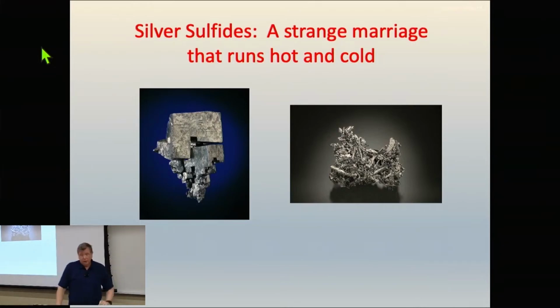So the classic way to look at that is acanthite. When we go buy an acanthite and we find a nice one, that's a Guanajuato piece there on the left-hand side, it looks cubic. In fact, that is the high temperature form of silver sulfide. But as we lowered the temperature, it froze in that structure from the visual perspective, but internally it has a monoclinic structure. All those sulfur bonds to the silver bonds snap back into a different direction, but left the outside looking like this. So it's kind of like a pseudomorph, but not really.